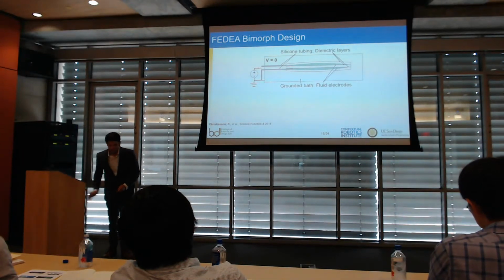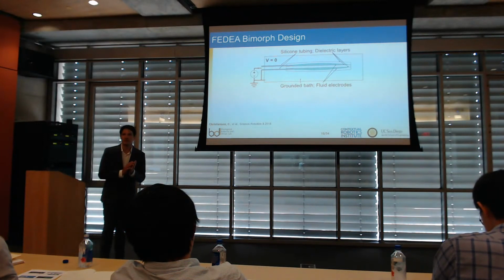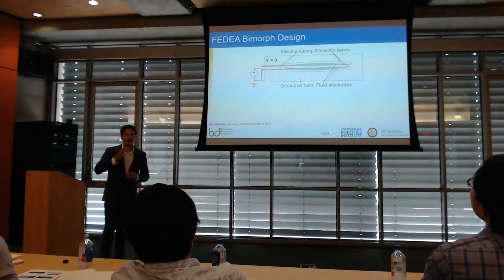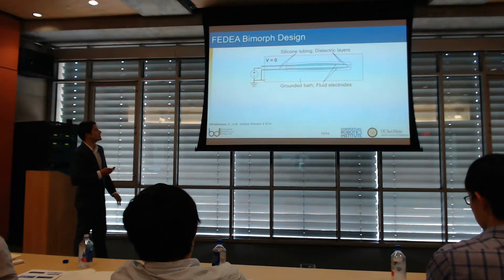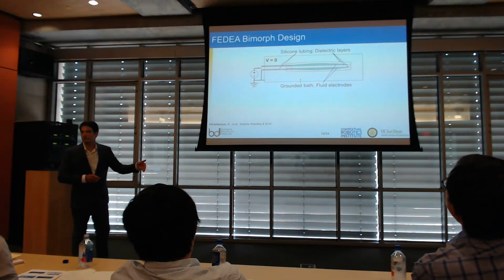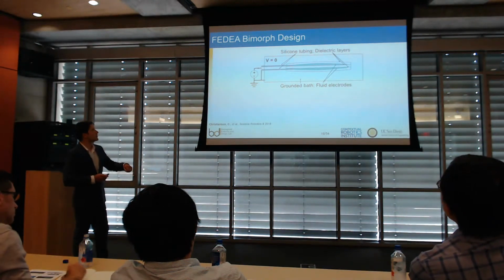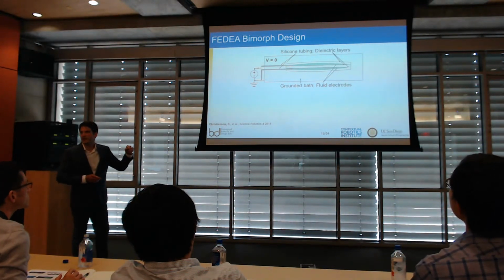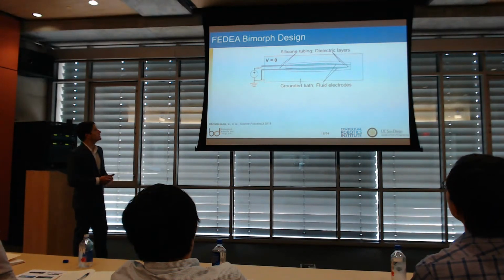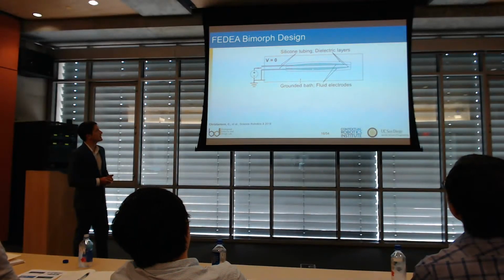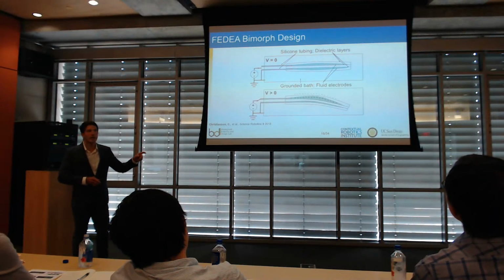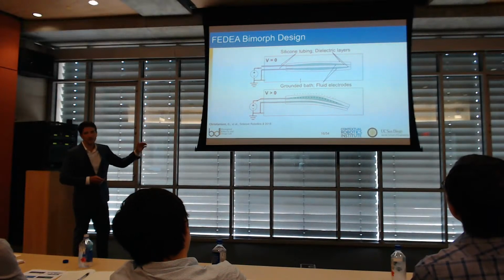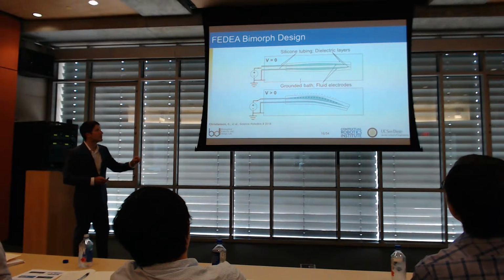So how do we do it? I made a bimorph actuator for the eel-inspired robot. The bimorph means that it can bend in two different directions. We put this in a tank of water that's grounded, so it's connected to ground. And then we have fluid pouches inside this actuator. In green here, the green on the inside is water, and there are 3 layers of a dielectric elastomer. As we apply a voltage between one of the pouches and the outside water, it will compress one side of the actuator and cause it to bend one way. Or we can apply the voltage to the other pouch to bend the other way.